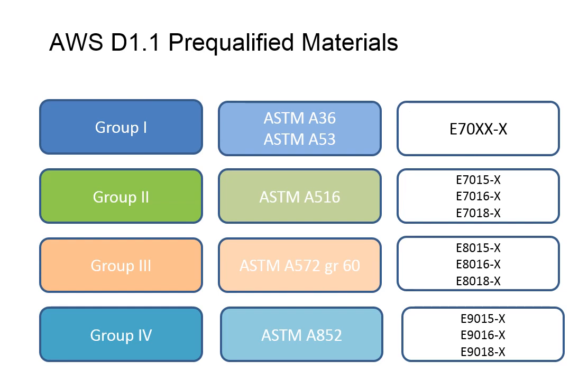But there might be a situation with the thicker materials. You're going to need a little bit of preheat, and you're probably not going to need some post-weld heat treat. But it's telling you in that group 2, if you read through AWS D1.1, it's a little more testy. Those materials take a little bit more care. But for the most part, if you act like a professional in the welding industry and you follow the rules, you're probably not going to get in too much trouble with those materials.